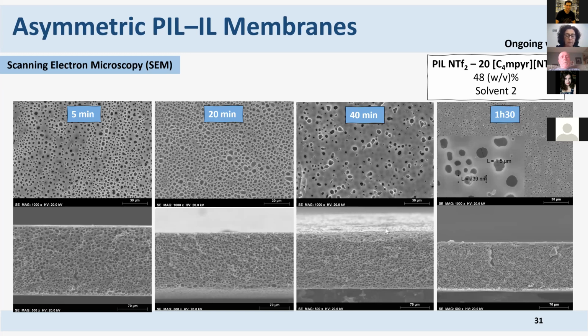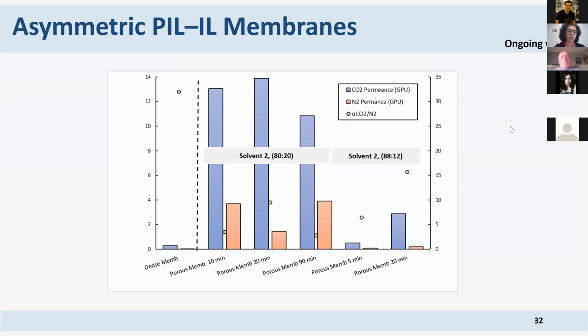So let's take a look at the membranes. These membranes look quite nice, and we were able to measure them. And here I have a comparison for you of the results that we get from the dense membranes and the results that we got from these last membranes with solvent 2. So here you can see that they are porous. So I have the permeances here, and the separation efficiency is here. Here we measure the separation efficiency of CO2 and N2.